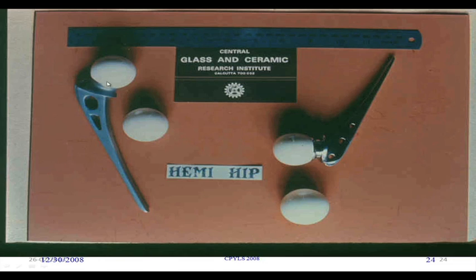This is alumina or zirconia. Zirconia can be used or alumina can be used, but here the coating may be primarily of HAP coating, either by plasma spraying or by biomimetic coating one can also use, but also by sol gel coating. So, different kind of coating techniques can be used, but the most convenient or useful is plasma coating. The stem can be used either of stainless steel or the titanium alloy.